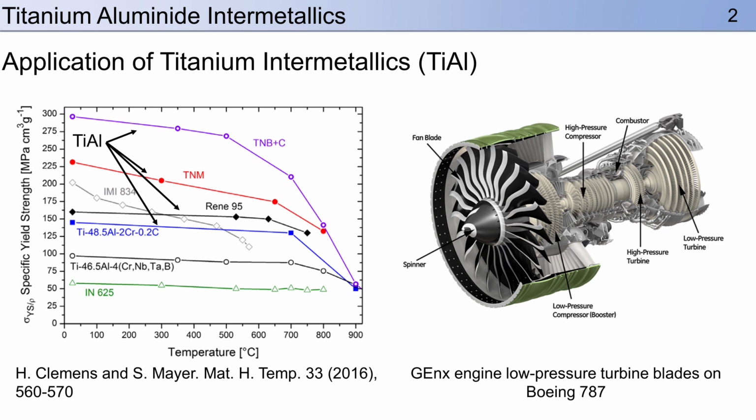Titanium aluminide alloys offer significant benefits over other alloy systems, particularly in aerospace applications. They are significantly lighter than titanium alloys and are dramatically lighter than nickel-based superalloys. They have a specific elastic stiffness 50% higher than other materials used in aerospace. They have high tensile strength and creep and corrosion resistance in the 600 to 800 degrees C range, as they have stable microstructures at these temperatures. And finally, they are more burn resistant when compared to titanium alloys. These qualities make titanium aluminide alloys an excellent choice for aerospace applications such as turbine blades.